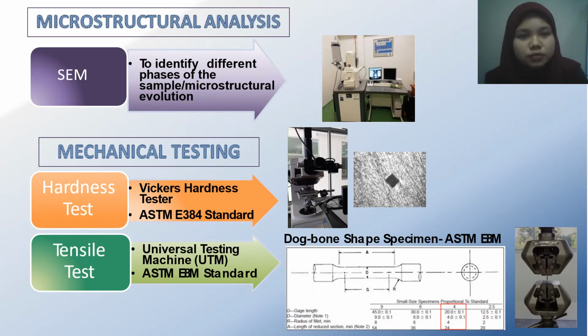So from here, the microstructural analysis by using the SEM is to identify different phases of the sample or microstructural evolution. And for the mechanical testing, the hardness test, I used the Vickers hardness test, by using the ASTM E384 standard. And the tensile test, I used the UTM by using the ASTM E8M standard.